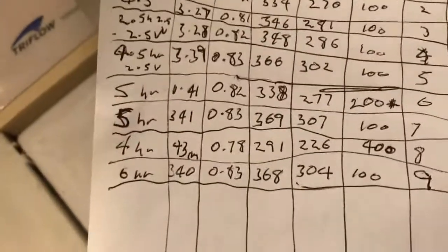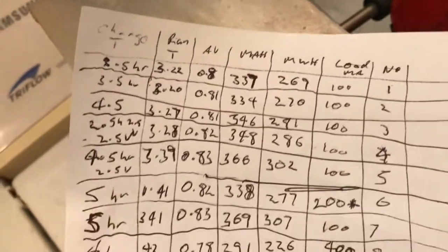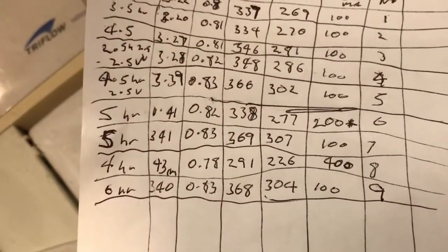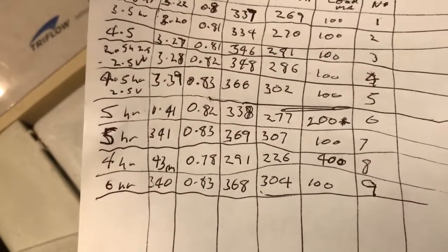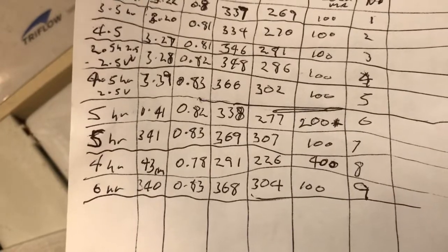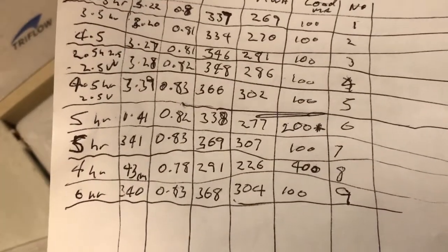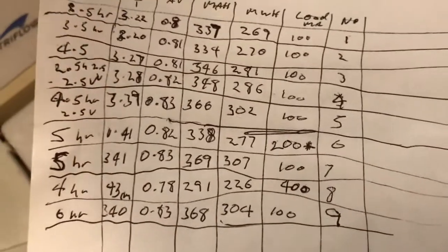The little results aren't too bad. We're around about 300 milliamp hours. That's the milliamp hour line. So with a 6-hour charge there, we got 368 milliamp hours and 304 milliwatt hours on the 9th charge.